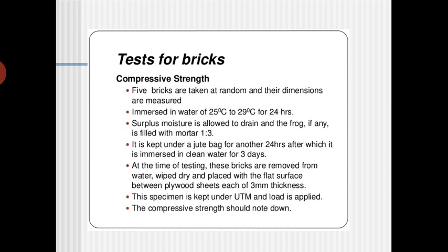Whatever moisture is there is allowed to drain, and the frog also is filled with mortar of 1 is to 3 composition. Then it is kept under a jute bag for 24 hours, after which it is immersed in clean water for 3 days. Again you have to immerse it for about 3 days.